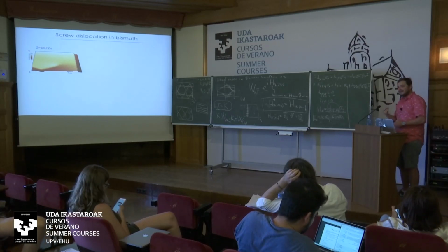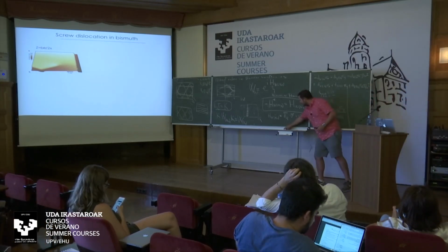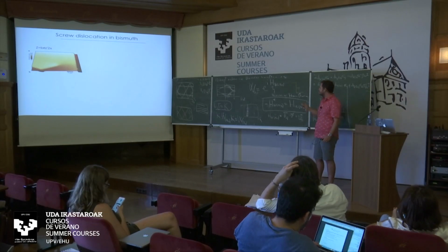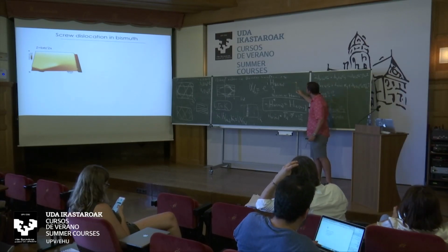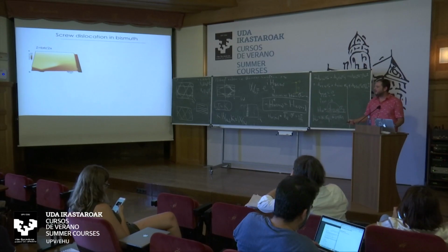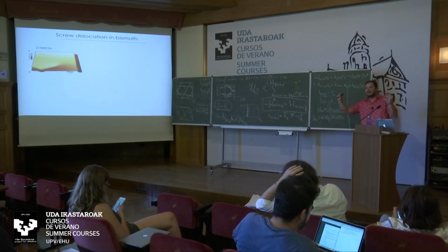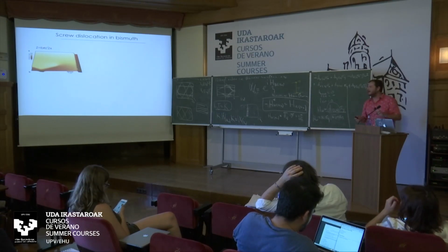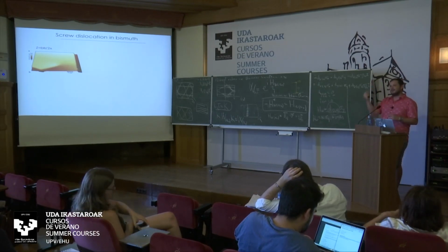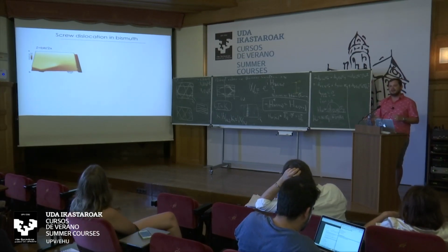Now, another interesting aspect that we discussed yesterday is that basically this step edge is not really a mathematical 1D object, but it's basically the smallest possible two-dimensional side surface that has two one-dimensional hinges. So this is what happens along this step edge. We have a very tiny side facet, 4 angstrom high in bismuth. This is the height of a bilayer with 2 hinges on top and below, which then terminate at the screw dislocation, which is a truly one-dimensional object.